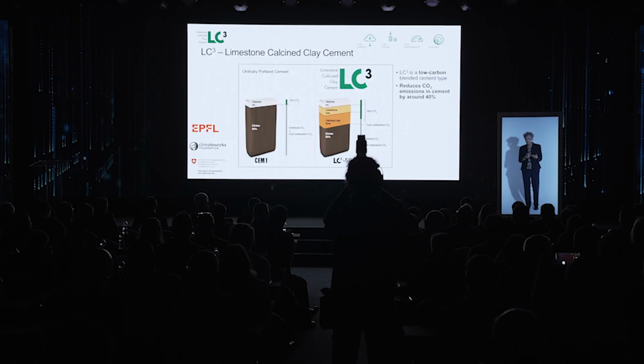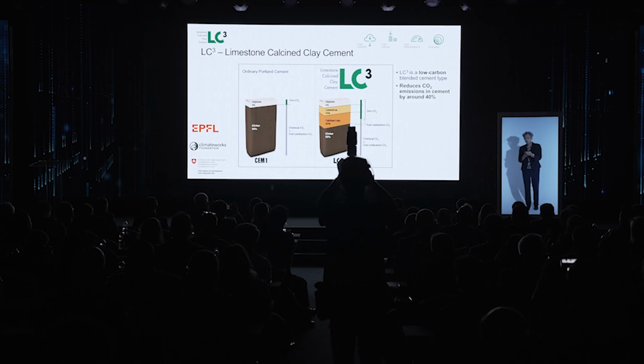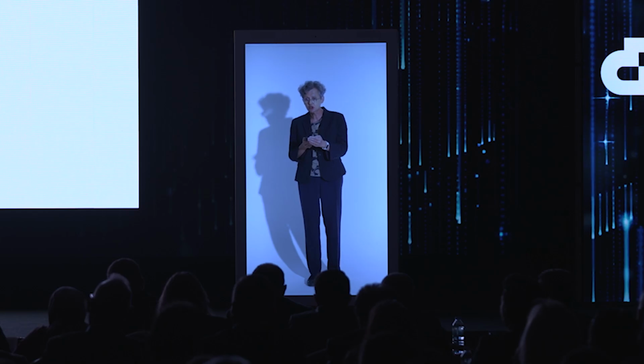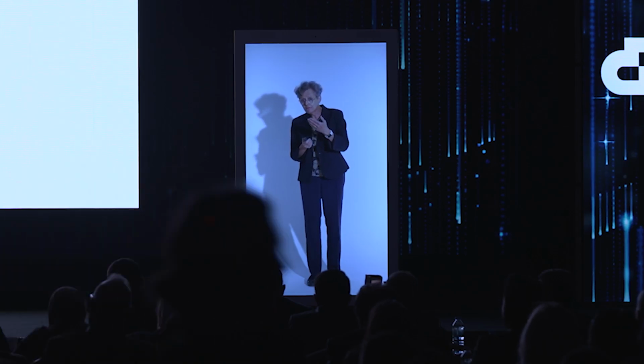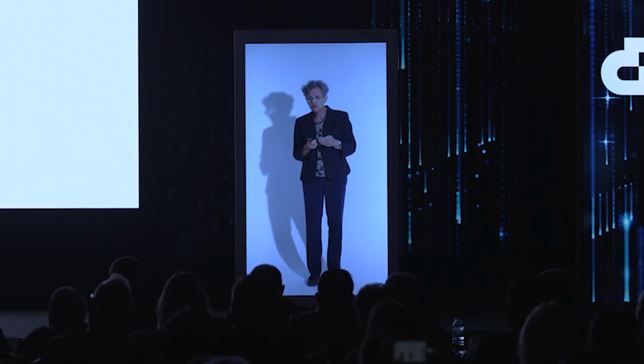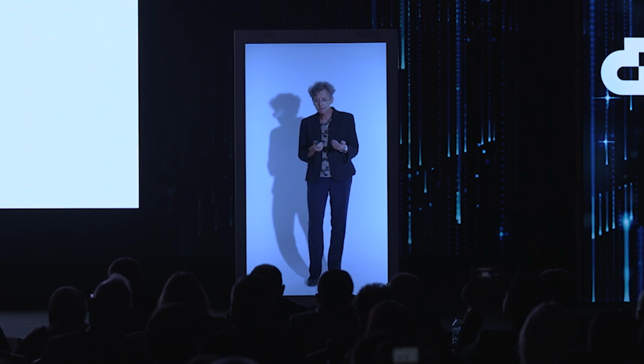What we have that's really underexploited are these clays, which can be calcined, that means heated up, to produce a very active substitute material. So this is the basic idea of LC3, limestone calcined clay cement. It is just another blended cement, but because the calcined clay is very reactive, we can go to very high levels of substitution, and we can maximize the incorporation of limestone, which is super abundant.